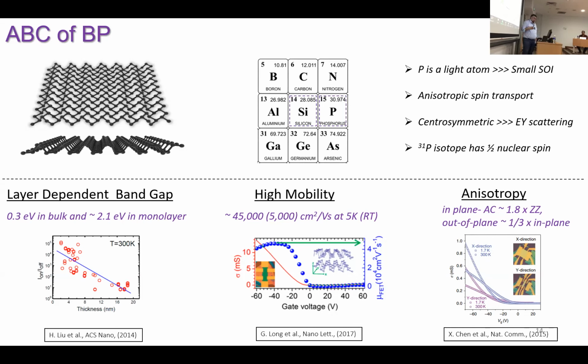But what about spintronics? Why is black phosphorus interesting for spin transport? You can see in this cropped periodic table that it is very close to silicon, which is kind of the star material of spin transport. And phosphorus is also a light atom, so hopefully it means that it should have a small spin orbit coupling strength, which would translate into long spin relaxation lengths. And with this material we now have the opportunity of trying anisotropic spin transport because of its crystal structure, which was not possible with any other materials in the literature.